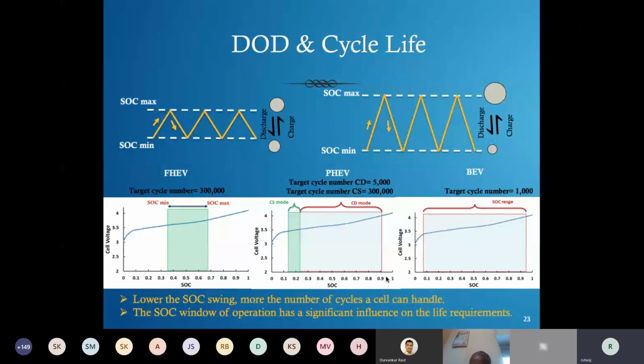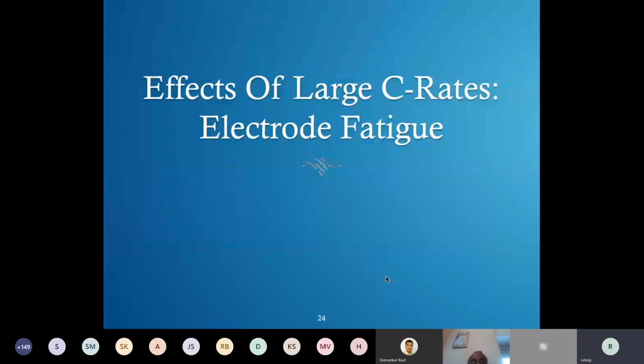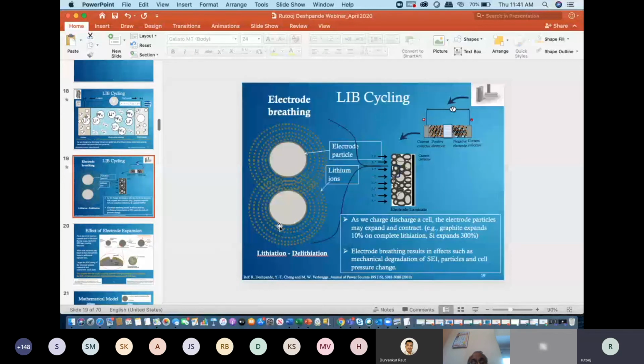If you look at batteries used for hybrid vehicles, full hybrid vehicles specifically, the batteries can handle up to 15C, 20C. I've seen batteries handling 20C instantaneously, and maybe 5C, 6C continuously. So it really depends on the electrode structure, how densely your electrode is packed. Higher energy density means all the electrode particles are close together. If you want higher power density, then you will have to separate these particles out. So you will have more porosity for lithium ions to travel, and then you would get much higher C rates that the battery can be used at.